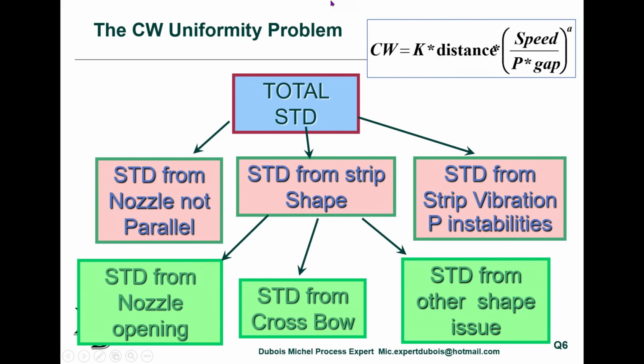So the final coating weight depends on nozzle to strip distance, depends on speed, depends on the piping pressure and nozzle opening, because this directly impacts the force that is induced by the air nozzle. So indeed, the variation, the total standard deviation, as already discussed, could be from non-parallel nozzles. I mean, the nozzles are not parallel to the strip.